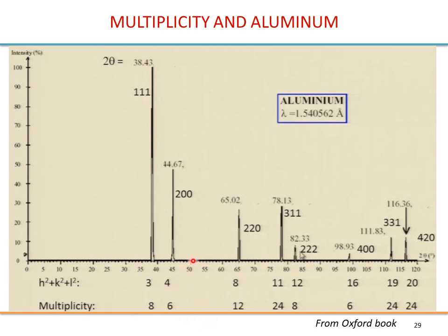Then if you compare 6 and 12, this one is supposed to be greater, so probably the Lorentz factor is affecting this, and this is higher than it should be. 12, 24, 24, so it is a bit greater, but not that much, so still an effect of the Lorentz factor.